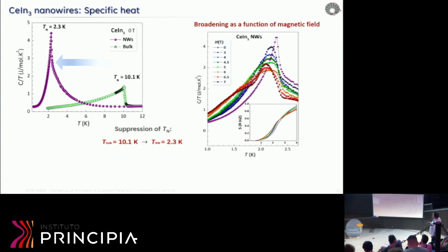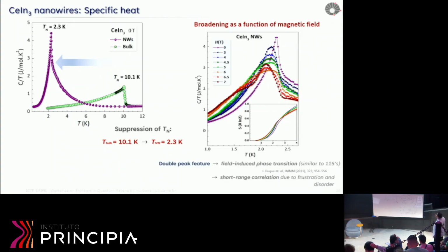And when we apply field, let me see, oops, it didn't work. What I was supposed to show here is this dependence with field: the peak shifts and broadens, and it eventually shows a double peak feature here. That was observed before for some sort of disordered or frustrated materials in 115s, and indicates a field-induced phase transition or a short-range correlation in these materials.